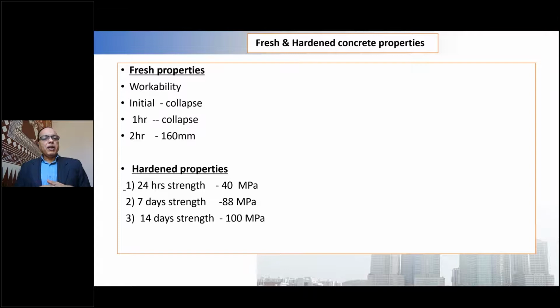And what are the properties? The initial slump is collapse, 1 hour also is collapse, and after 2 hours it should have a slump of 160 millimeters. And look at the strength requirement. 24 hours you require 40 MPa. In 1 day it should get so much of strength. 7 days 88 MPa, and 14 days 100 MPa was the strength requirement.